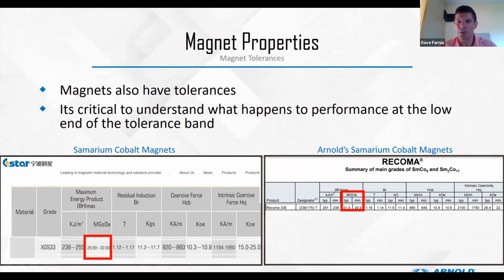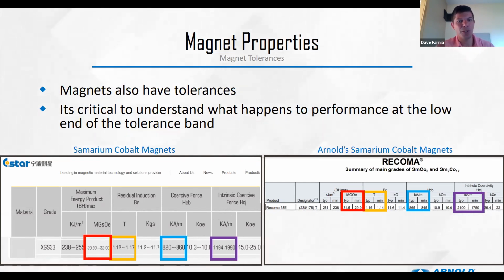We start digging into that performance, we see that our minimum BR for 33 is 1.14 versus 1.12. So much tighter range on our remnant flux density. Same holds for our coercivity, our HCB, the 820 to 860 versus 845 to 865. So we try to hold a much tighter range on our coercivity. Also really falls into the intrinsic coercivity, which before I got to work with a magnet manufacturer, I did not care about. So when I'm looking at the magnet model in JMAG, I care about the BR and I care about the HC. So I'm looking primarily at the second quadrant of the magnet.